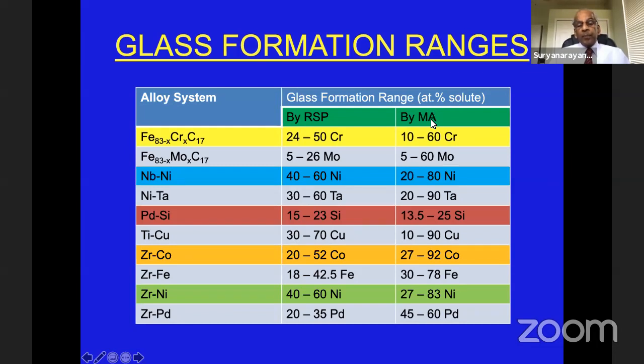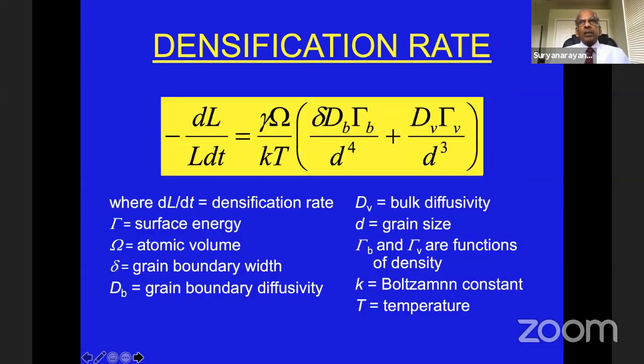The reason being the amount of departure you can achieve by mechanical alloying is more than what is possible by RSP methods. Now, these nanocrystalline materials sometimes become very difficult to consolidate, and this is the way you can think of a consolidation rate or the densification rate equation, where there are two very important things. One is the bulk diffusivity, and the second is the grain size.